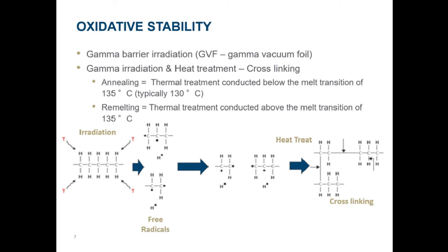Oxidative degradation can be prevented by removing free radicals, and one way to do this is through heat treatment. Heating the material mobilizes the polymer chains, allowing the free radicals to recombine, as long as full recombination occurs, then the oxidation cascade cannot occur. During this recombination, cross-linking occurs. But the mechanical properties are also affected. This means that a compromise is required in defining heat treatment specification, and not all heat treatments are the same.